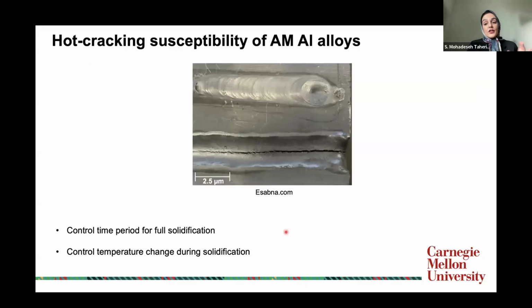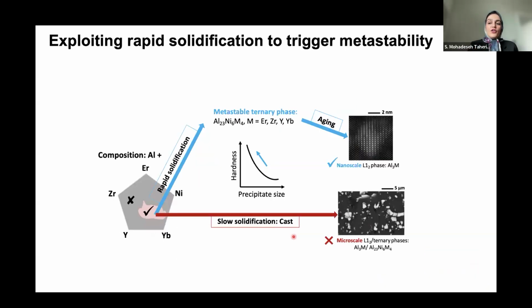As I said, you have to design it to inhibit the cracks, and we do it by controlling the solidification characteristic, meaning the time and temperature range during solidification. But we also had an idea to improve the strength of an alloy that I will share with you here. We found that if you are in these five elements' compositional space, first you have to choose the composition smartly. If you are in the correct composition zone and you apply rapid solidification, like what happens in laser powder additive manufacturing, you can block the microstructure of the alloy, meaning what you can see under the microscope, in a metastable state.